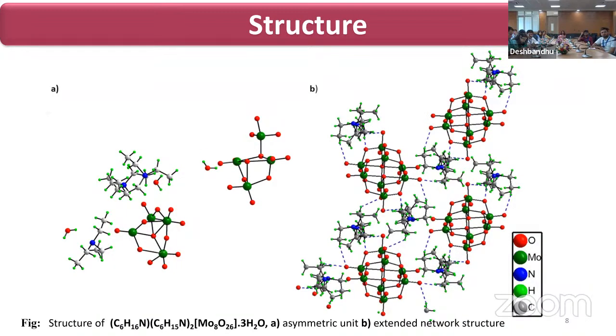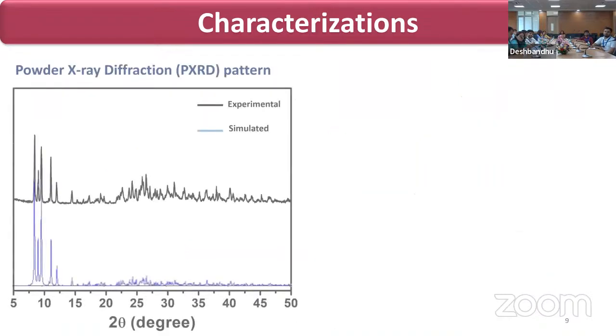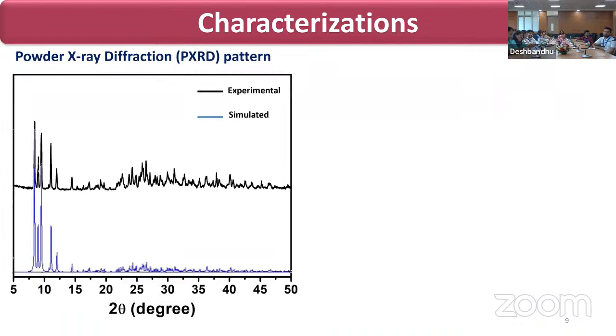These crystals were characterized with single crystal XRD, in which the asymmetric unit consists of two half octamolybdate clusters surrounded by three triethylamine ligands and water molecules, which when joined together by hydrogen bonding form an extended 3D network-like structure. We have characterized it by powder XRD. We have matched it with the single crystal XRD and the powder XRD pattern to ensure its phase purity.